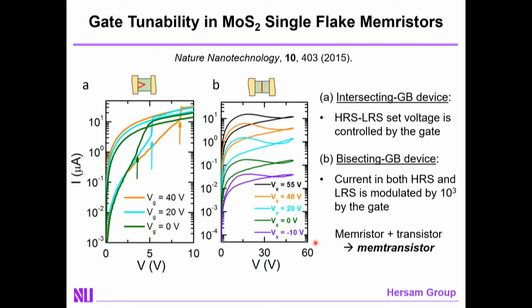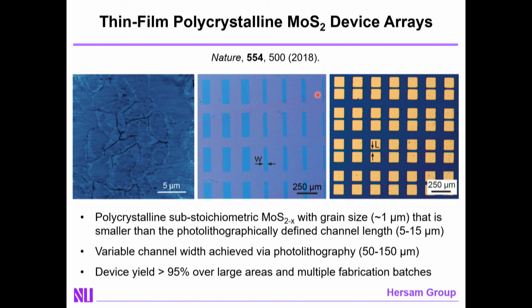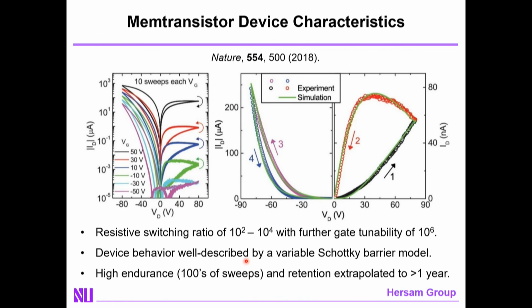Now the problem in this early work is that when we had a small number of grain boundaries per device, there'd be great variability from device to device because it would depend upon the geometry of the grain boundary with respect to the channel. However, we're able to get around that issue by going to even smaller grain size MoS2, which implies that at the device level, we have many different grain boundaries present. And as a result, you get an averaging over the stochastically distributed grain boundaries at the single device level. This substantially improves device yield and homogeneity from device to device in the array.